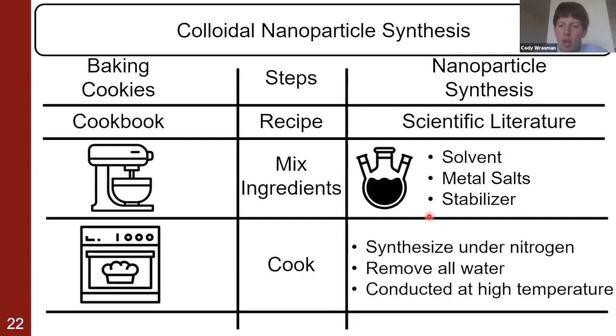Once you've mixed all of the ingredients, then you need to heat them up. In the case of nanoparticle syntheses, this heat up process is done under nitrogen, both to reduce flammability hazards and to exclude oxygen from being incorporated into the nanoparticles. Likewise, it's important to remove all water since we are going to high temperatures. It would boil off violently at such high temperatures. And as I mentioned, these syntheses are conducted anywhere between 300 and 450 degrees Celsius.